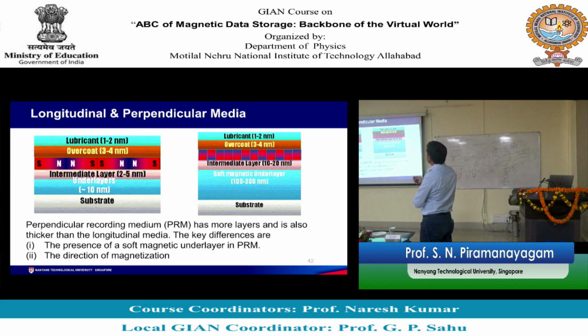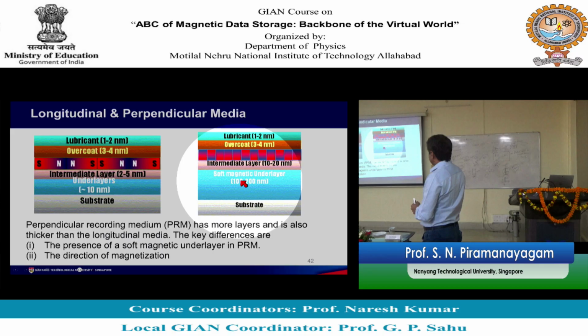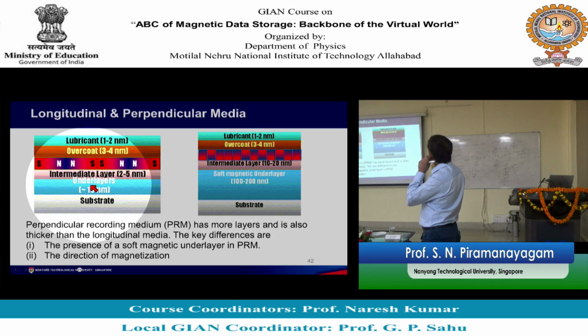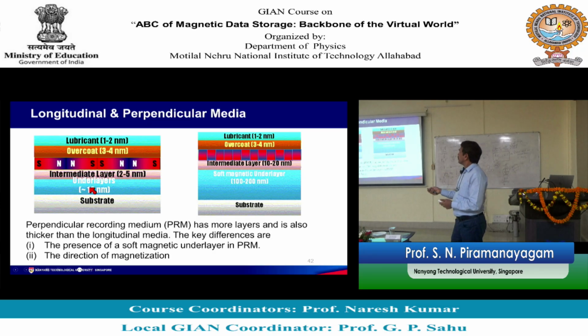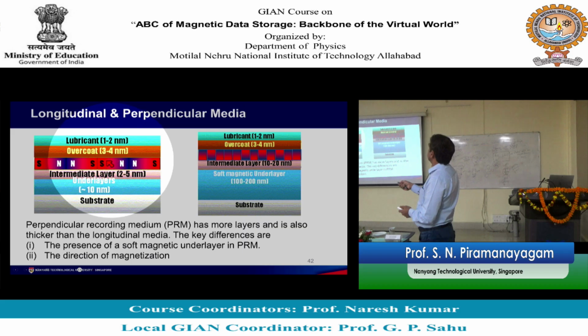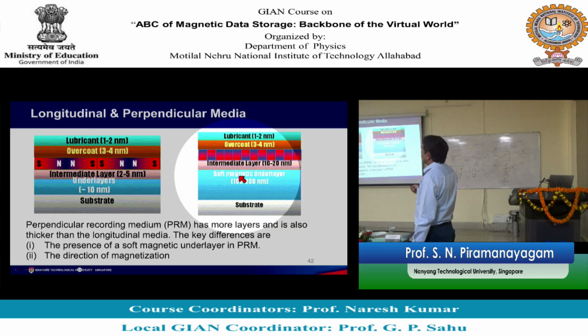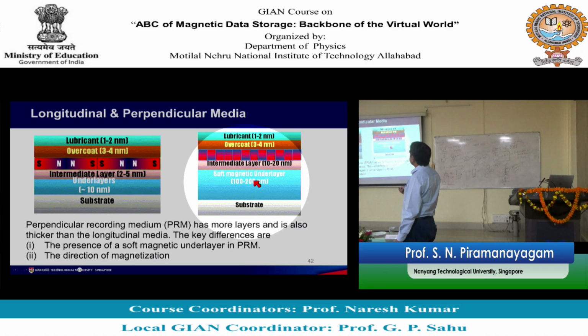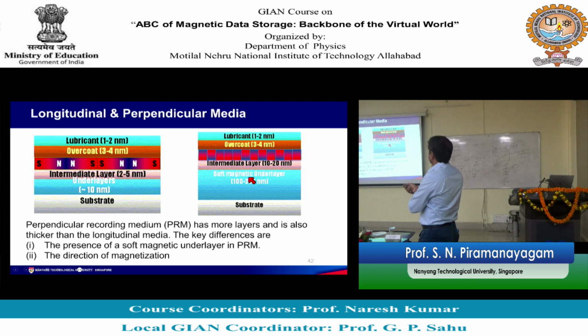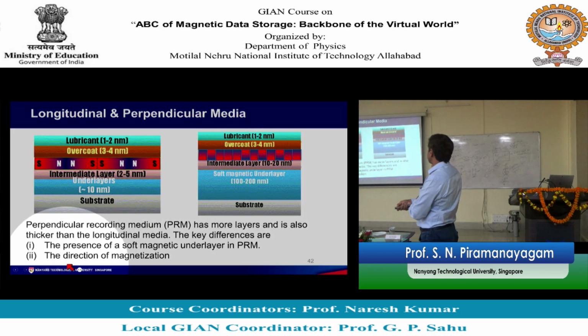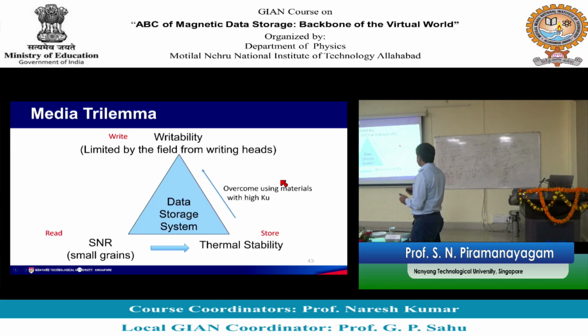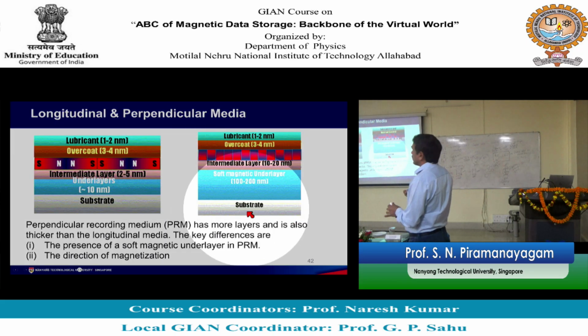Now, when you come to the perpendicular recording technology, one difference is that the magnetization is now perpendicular, not horizontal. And the second difference, now you see that there is a soft magnetic underlayer. Okay, here the underlayer was non-magnetic. So here the only magnetic layer is the one that stores the information. But in perpendicular recording technology, we have a soft magnetic underlayer. Okay. So that's another difference. So the two differences are the direction of the magnetization and the presence of the soft magnetic underlayer. Okay, so I'll explain why we have a soft magnetic underlayer and how we use it in the next few minutes.